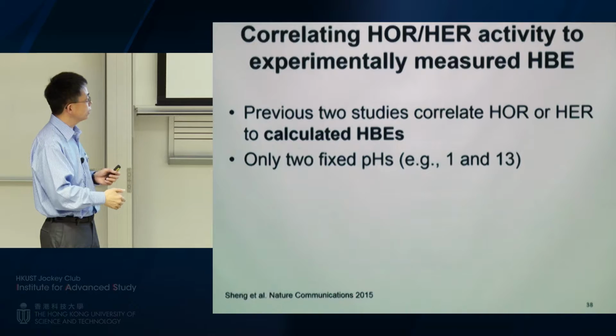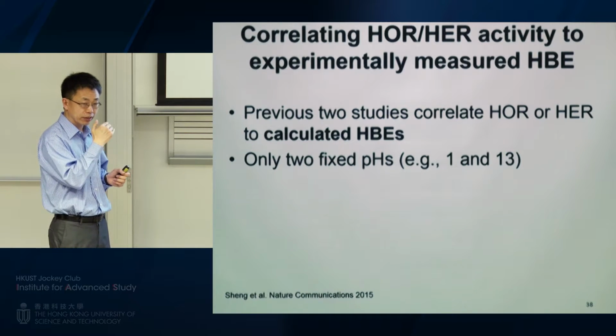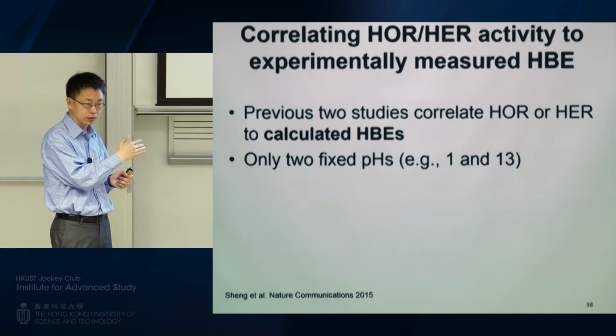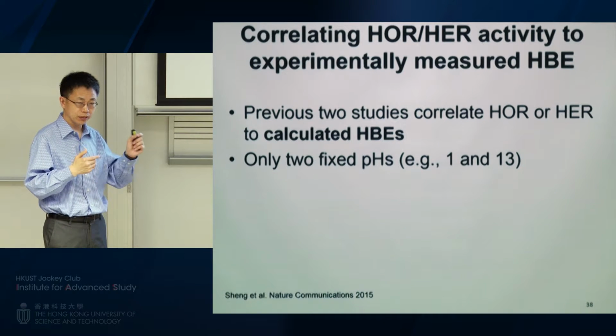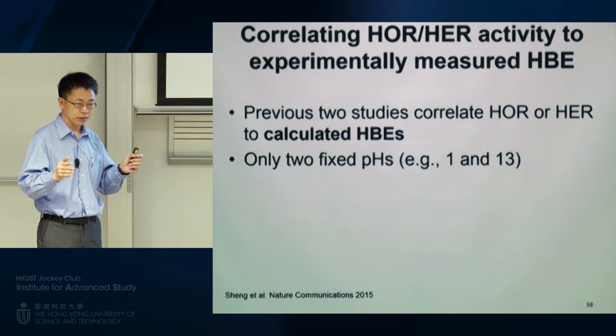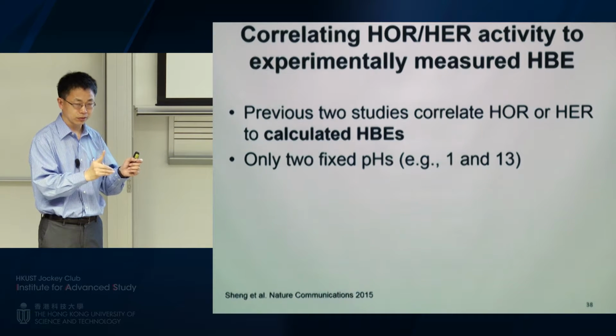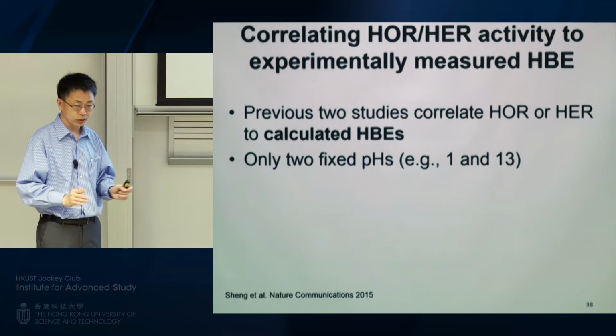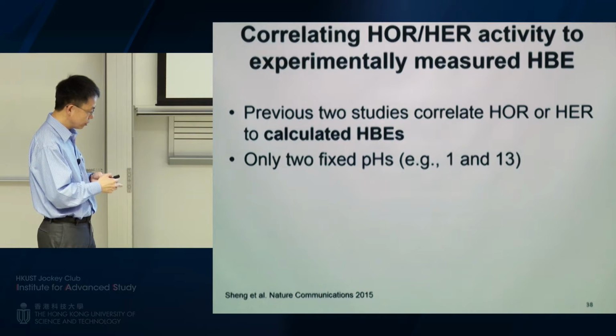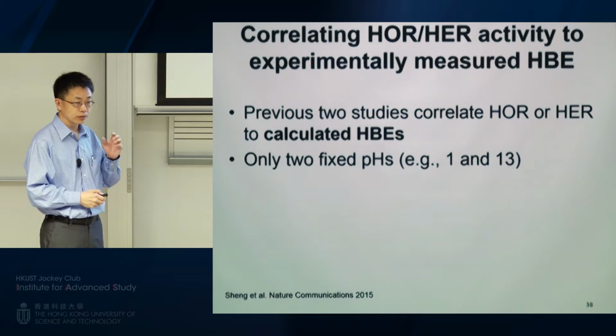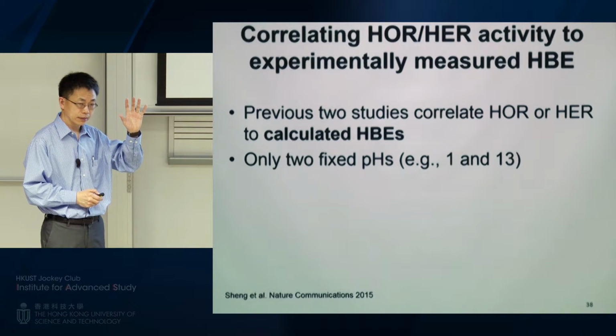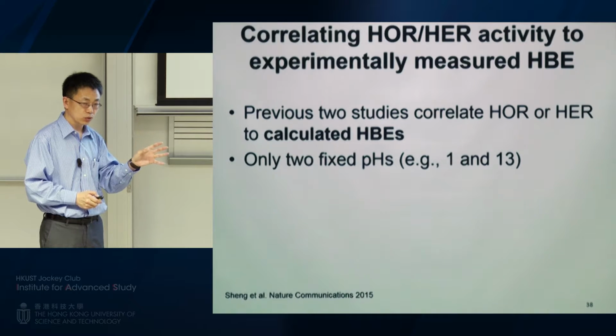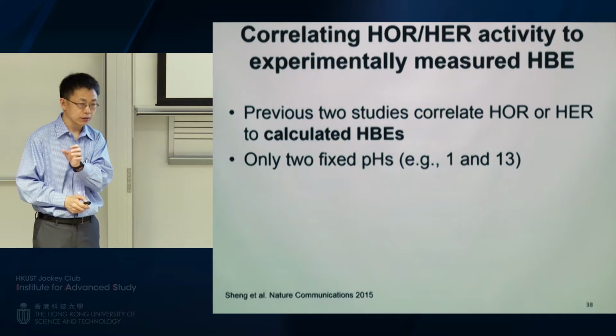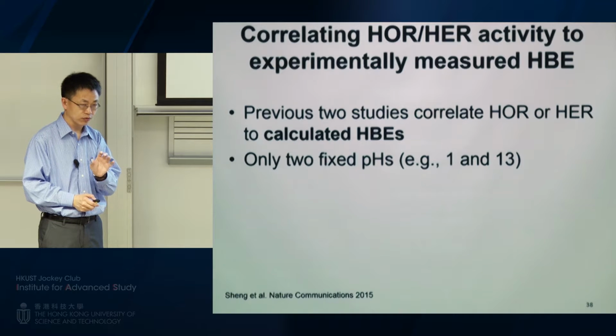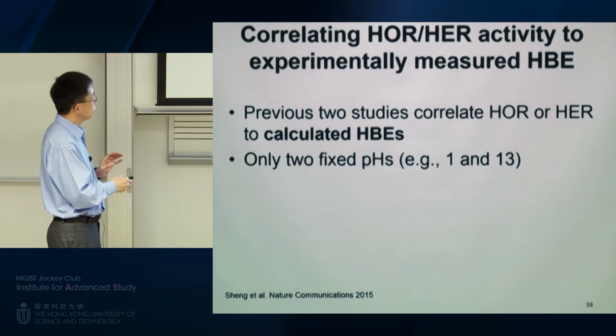And if you look at the pH, their work was in acid. Our work was in base. So pH 1 versus pH 13. And there's nothing in between. So this is another gap. There's no study in between these two extremes of pH. So what we wanted to do is correlate the activity to an experimentally measured hydrogen binding energy for the first time. So that was the goal. So this is how we did it.